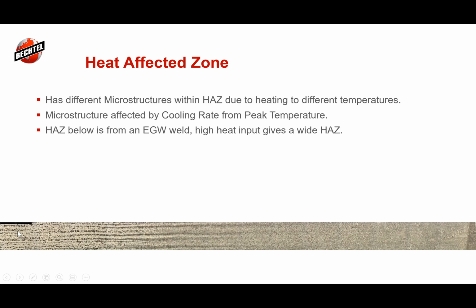You can see this banded. It looks like there's bands in it. That's the banded ferritic pearlitic microstructure. And you can see as the heat dissolves that away, as it got to higher and higher temperatures, then you see those bands get dissolved as the material was heated up so much and was at high temperature for so long that it caused all of the atoms to move around and completely change themselves. In fact, as we get over here, it's really hard to tell, but the whole grain structure and everything changes. And this was never liquid. We're just looking at a heat affected zone.